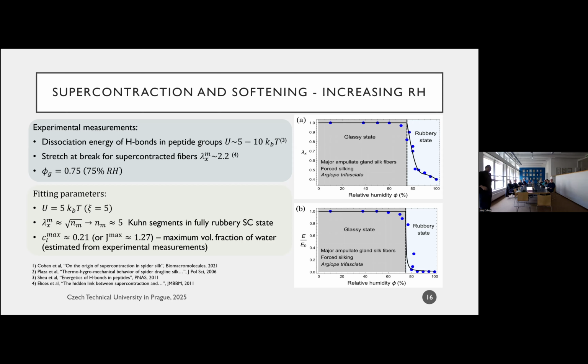So for example, in the model itself, I need to input the dissociation energy of a hydrogen bond. Now, people have actually quantified this using MD simulations. There was a paper in 2011 that looked at the energetics of hydrogen bonds in peptide groups. And what they found is that the dissociation energy of hydrogen bonds in a peptide group should range somewhere in the area of 5 to 10 kT, right? So this is the limit that we have to play around with.